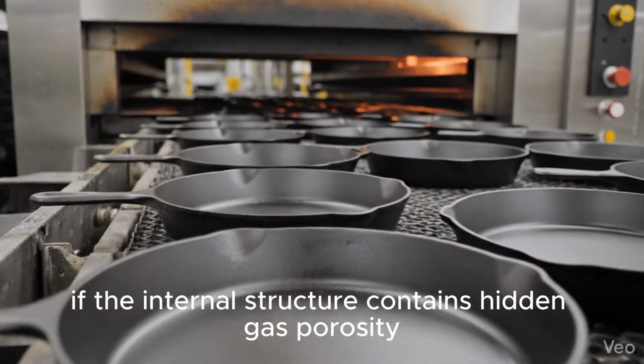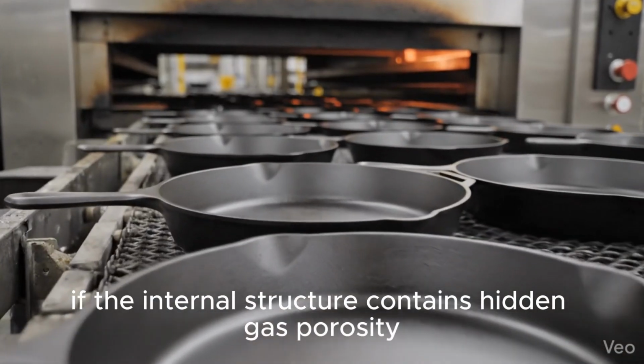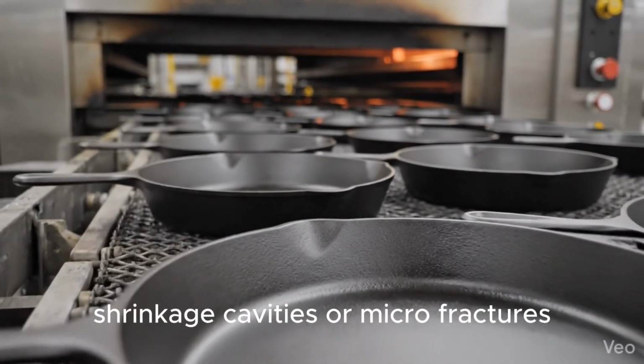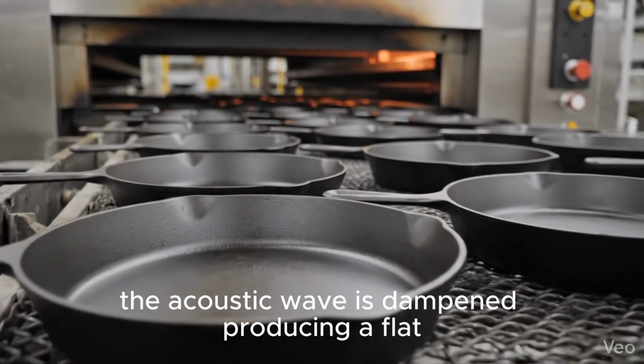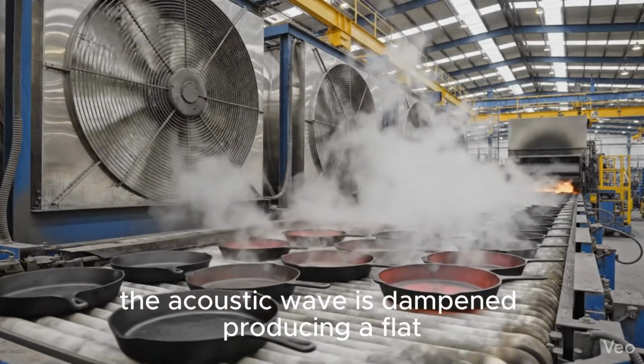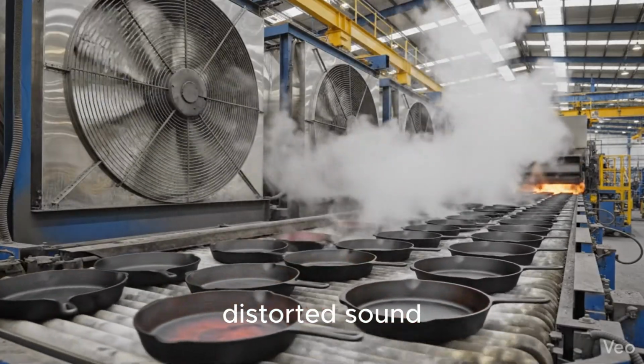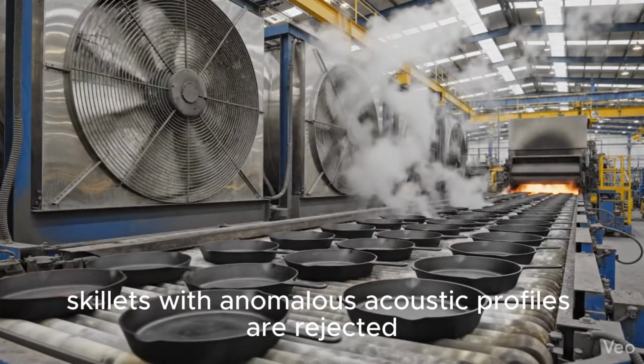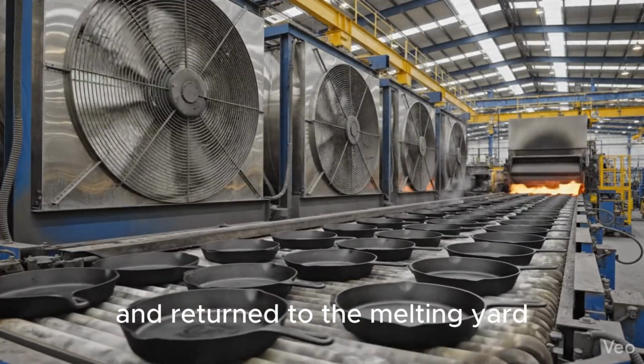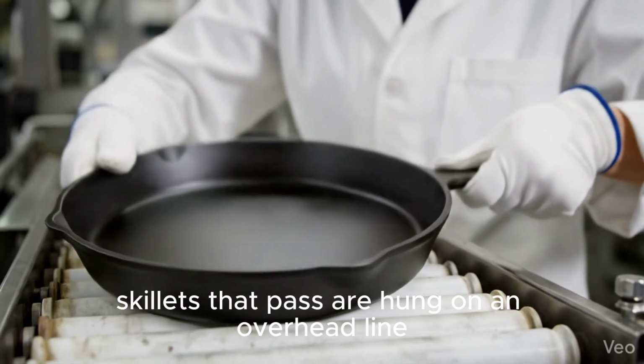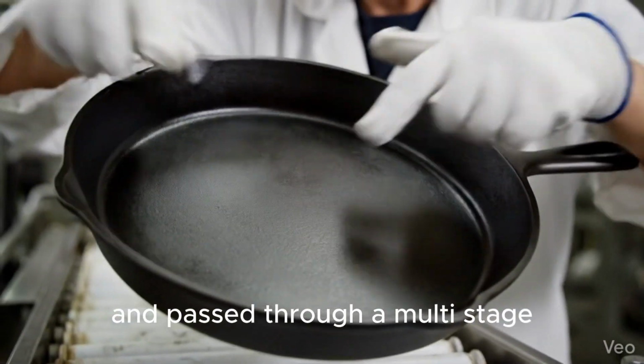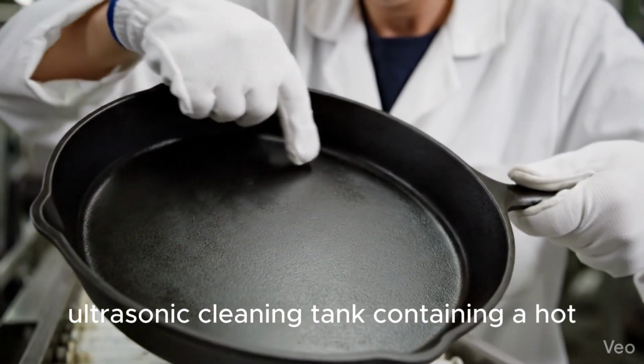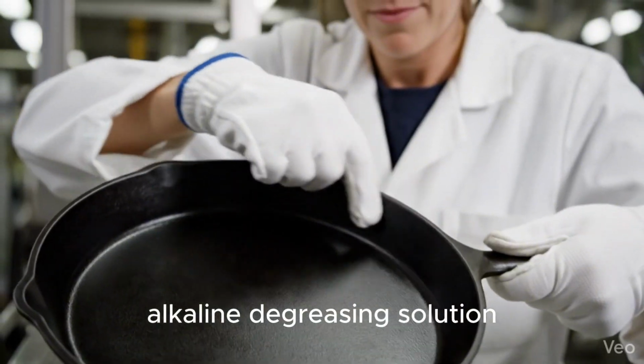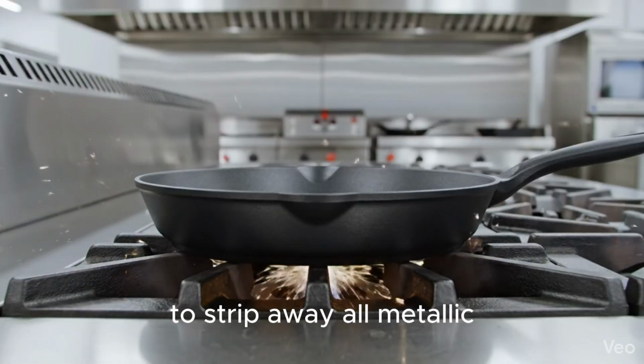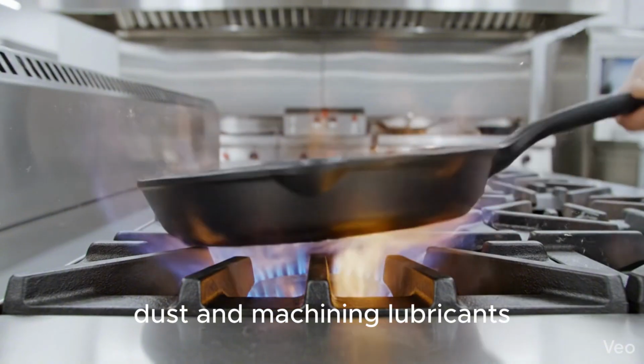If the internal structure contains hidden gas porosity, shrinkage cavities, or microfractures, the acoustic wave is dampened, producing a flat, distorted sound. Skillets with anomalous acoustic profiles are rejected and returned to the melting yard. Skillets that pass are hung on an overhead line and passed through a multi-stage ultrasonic cleaning tank containing a hot alkaline degreasing solution to strip away all metallic dust and machining lubricants.